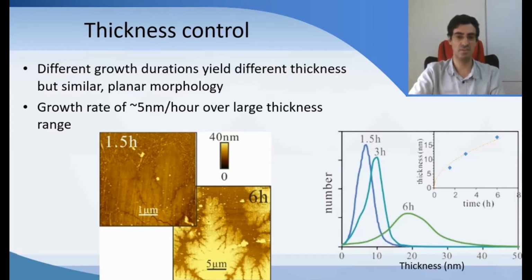Instead, we find that our thickness is following a diffusion law very well, and we can adjust the thickness pretty precisely, because every hour it only extends by about 5 nanometers. So that's the one interesting feature of using 2D materials interfaces for ordering.